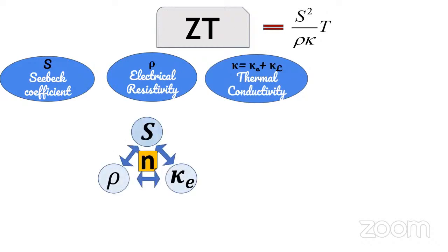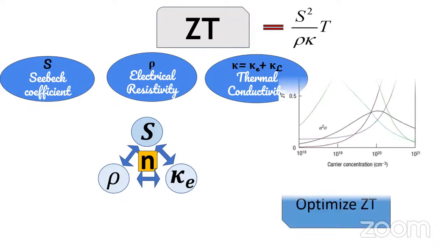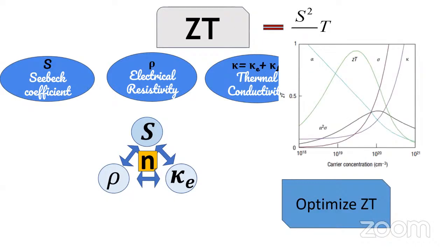But the main bottleneck is that S, rho, and kappa E are interrelated to each other via n, the carrier concentration of the material. To optimize the ZT value, n should be between 10 to the power 19 and 10 to the power 20, which was established by the Snyder group. So our central idea is to decouple the phonon and electronic parts by maximizing phonon scattering relative to charge carrier scattering, which lowers the kappa L. And kappa L is the only independent parameter.